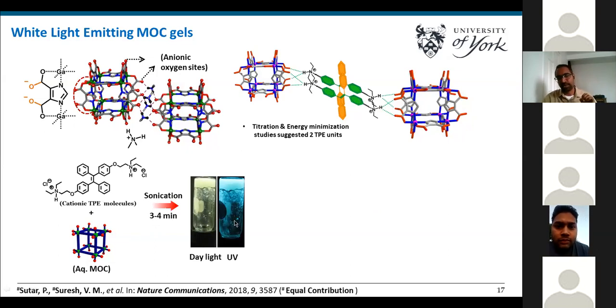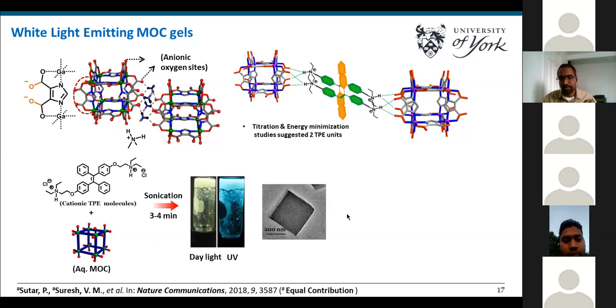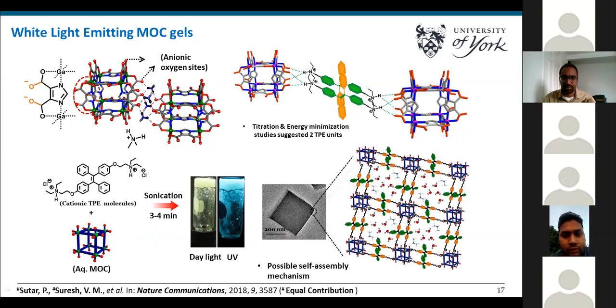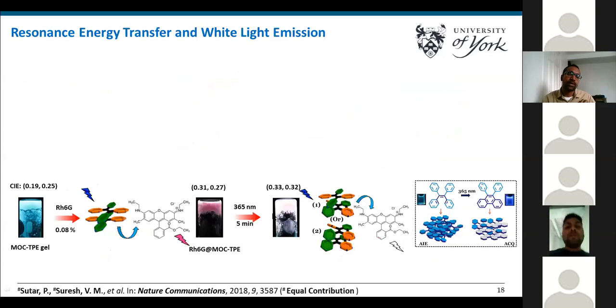As you see under UV light, this is strongly fluorescent with a cyan emission. The TEM analysis suggested cube-like structures in the gels, and we proposed an assembly like this, where metal organic cages are assembled by the TPE linkers, extending the assembly in a three-dimensional way, where the pores are filled with water and dimethyl ammonium cations, resulting in the stable gel formation. So now we have a stable metal organic cage gel with TPE within it, and it is highly fluorescent.